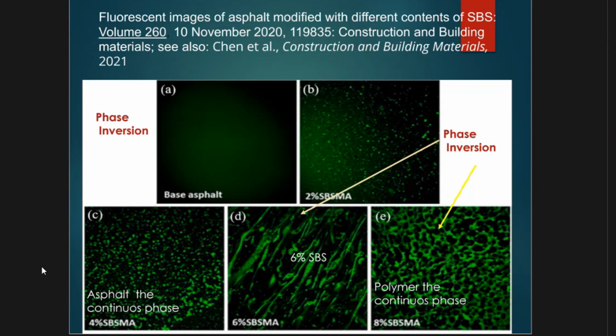Let me say something about the people who do aging of asphalt. If you did some aging of asphalt, in fact, the polymer can mask the aging of the asphalt. Just telling you that. And so we have this phase inversion. So those parameters generally are measuring the rheology of the continuous phase, in that case, the asphalt. So that's just for people thinking about what's happening. And why am I bringing this up? Because I think